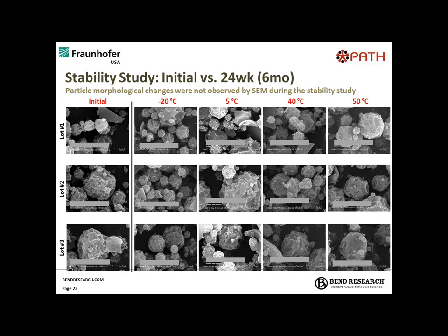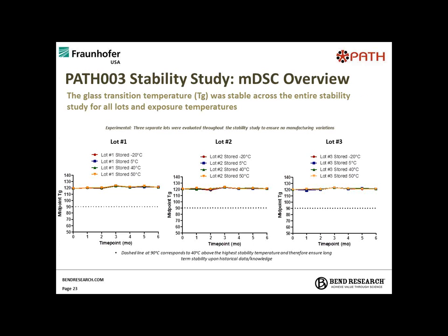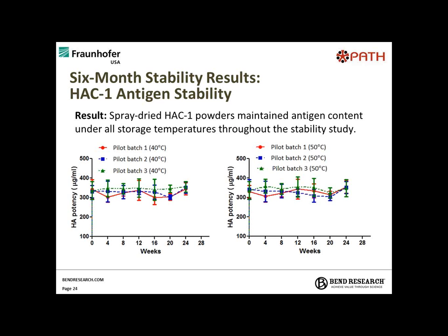Using this tool, the DSC, as well as things such as PXRD and SEM, we pushed forward and developed a protein formulation for a stability study, as shown here in this slide. We performed SEM across 6 months at a number of conditions from the stability study at negative 20, 40 degrees Celsius, 50 degrees Celsius, and saw stability by SEM. We also saw stability by DSC. We produced 3 lots, different conditions, and saw that the TG of this lead formulation held strong at 120 degrees Celsius, which is great, and did not phase separate.